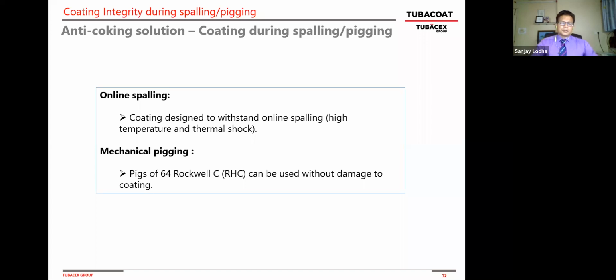Now, everybody has questions, and I saw some questions in the chat room: does this coating work with online spalling or steam decoking or mechanical pigging? So I just put a slide, and that should answer many questions. The coating is designed to withstand online spalling because it's designed for high temperature and for thermal shock, and the coating has the same coefficient of thermal expansion as the substrate. And as a substrate can change from P9 to 347H or anything else, we're able to customize the coefficient of expansion for each substrate.